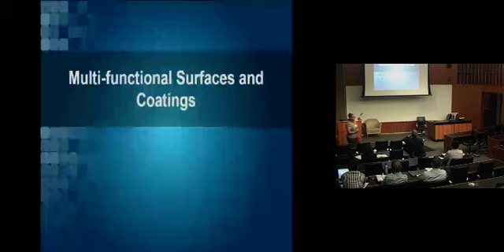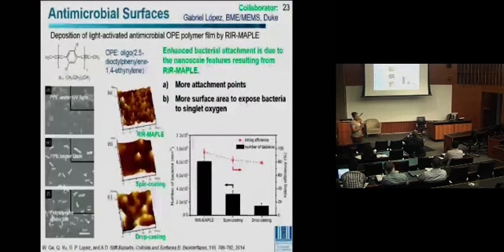And so my last example is multifunctional surfaces and coatings. Again, this ability to combine different materials in a bulk film with nanoscale phase separation means that you can make a bulk film with a unique property or function that's based on the components that you've put together. In this case, and this is work that I did with Gabriel Lopez, we first looked at antimicrobial surfaces. We looked at this OPE macromolecule, which has antimicrobial function if you shine UV light on it.